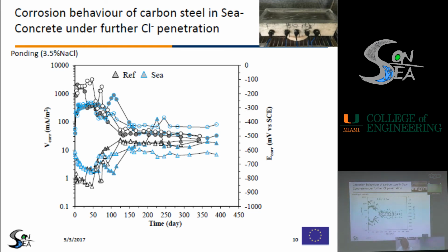In the carbon steel bar embedded in the sea concrete, we had from the beginning a quite low corrosion potential and a quite high corrosion rate, indicating that just a small amount of chloride was enough to promote the initiation of corrosion, indicating that the initial chloride content was just slightly lower than the critical chloride threshold. So in 1 year, corrosion occurred on all the carbon steel bar embedded in all the types of concrete, indicating again that the carbon steel bar was unsuitable to be used in combination with sea concrete.